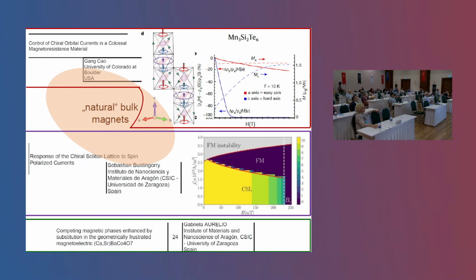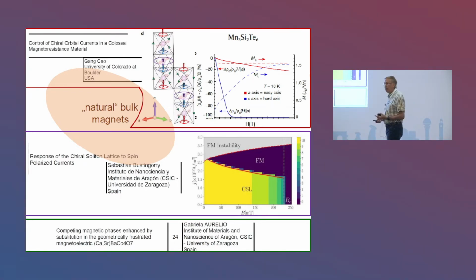natural bulk magnets. There were several very interesting presentations for me. One of them, for instance, on the material manganese silicon telluride, where a very interesting kind of colossal magnetoresistance effect was shown, which is not related to the full polarization of the spin system, like, for instance, in the double exchange manganites. It was argued that a very strong magnetoresistance effect in small magnetic fields, far away from the saturation magnetization, is due to a novel kind of interaction caused by so-called chiral currents on the atomic scale, probably existing in the transition metal oxygen octahedra.